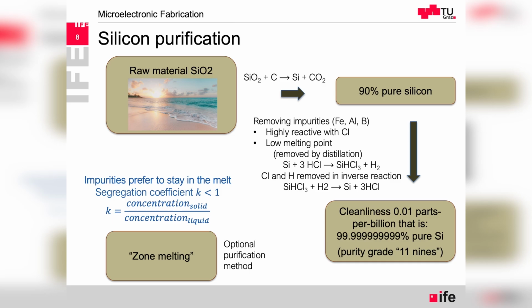If there are still some impurities that we want to remove, hopefully there are such impurities which have a segregation coefficient lower than 1, which means that impurities prefer to stay in the melt rather than in the solid material. So the segregation coefficient K tells us the ratio of the concentration of impurities in the solid to the liquid. When we have the silicon rod and we want to purify it, we simply melt a zone with AC fields, and we sweep this field by pushing the molten zone further and further, which contains all the impurities, and this improves further the cleanliness.